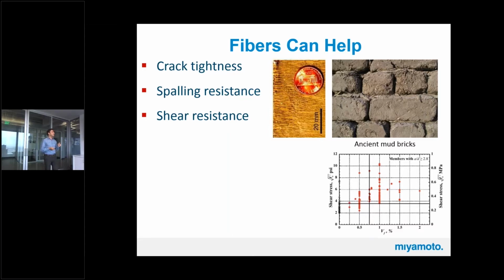Compared to pure concrete without reinforcing, if you have better shear resistance, you can provide a kind of confinement to the structure, self-confinement. It improves the energy absorption capacity of the building. The other thing is fiber reinforced concrete improves the bond. If you have a better bond between concrete and reinforcing, you expand the plastic hinge region. You would have a bigger plastic hinge, so you would have less concentrated damage. You would have higher energy absorption capacity in the structure.